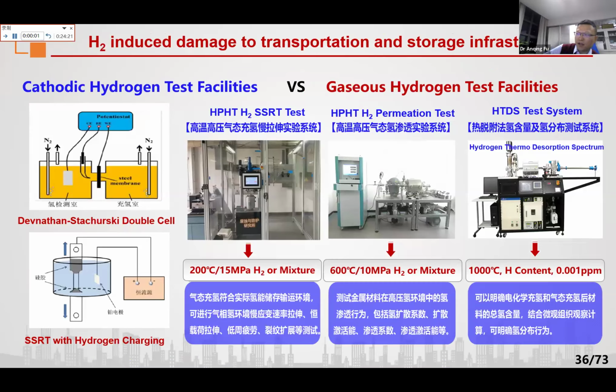In these slides, I compared the cathodic hydrogen test facilities and the gaseous hydrogen test facilities. You can see usually a very classic test method is the double D cell to do the cathodic hydrogen damage test, or the SSRT with hydrogen charging. This as well is cathodic hydrogen charging.